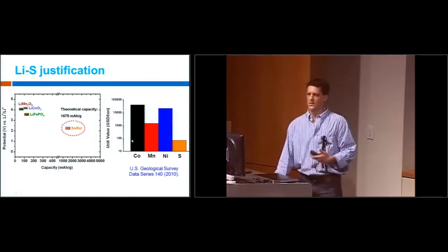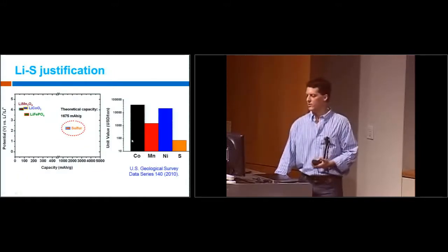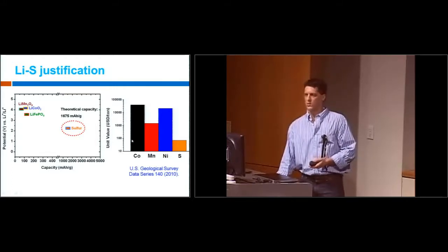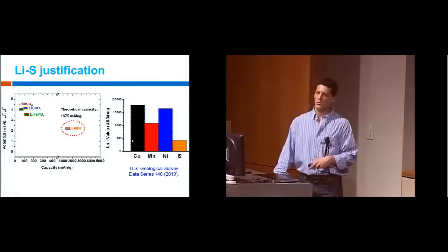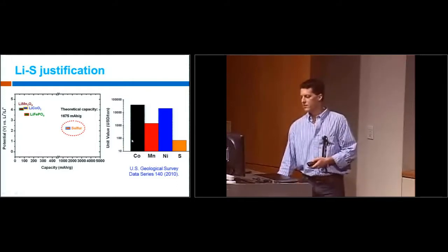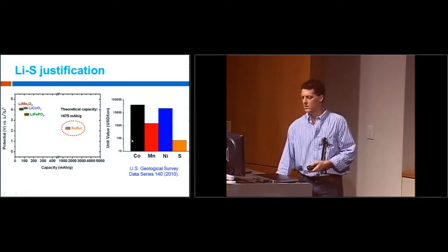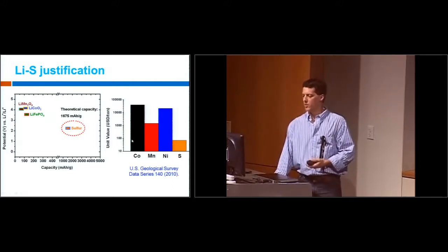Lithium-sulfur has been one of the most researched of these technologies. The reason that sulfur is an interesting material: if you look here, this is capacity, which is essentially the amount of electricity that you can store in a battery. On the capacity, you'll notice a break in the scale here. Sulfur nominally has 10 times as much capacity as the current materials used in lithium-ion batteries. These are basically transition metal oxides, and their capacity is somewhere around 140 milliamp hours per gram, whereas the sulfur is 10 times that.